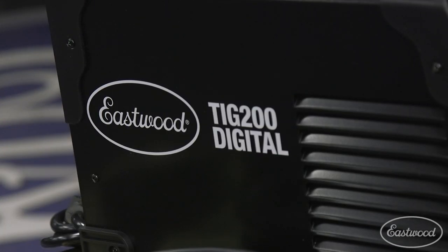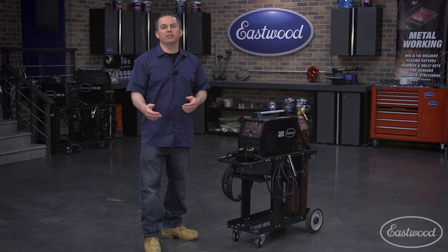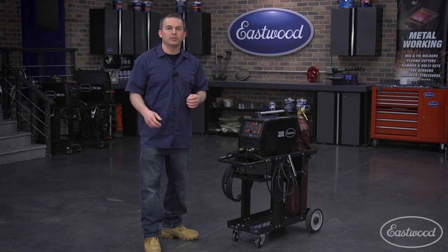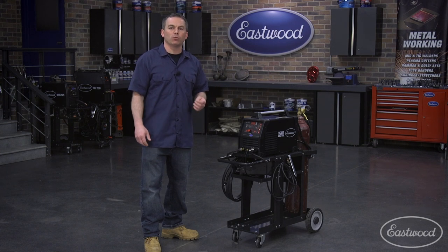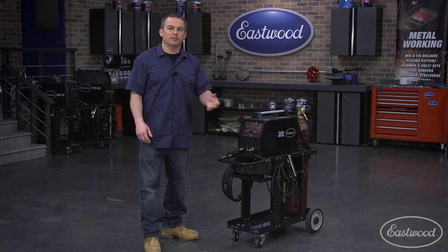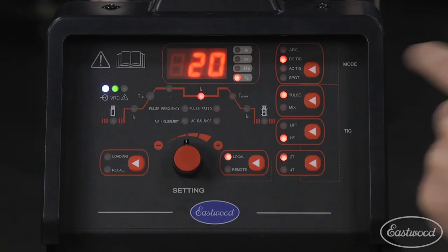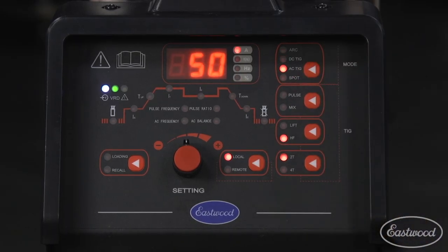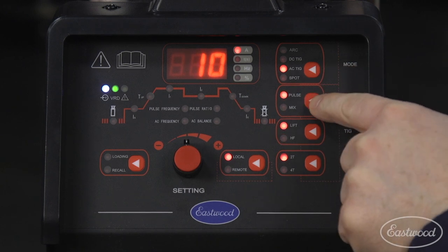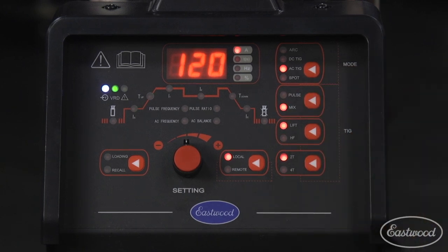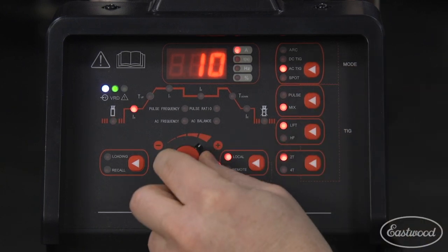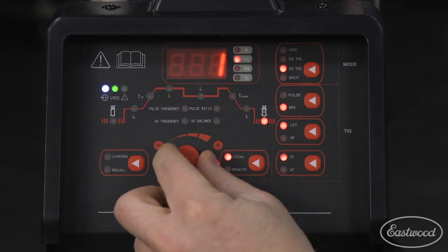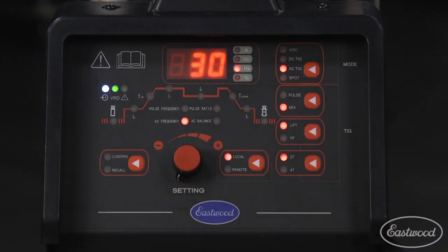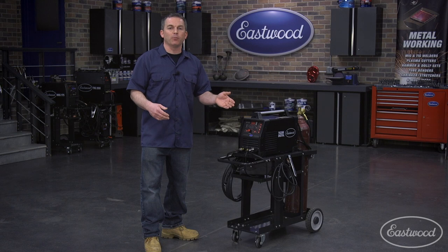The digital TIG also has mixed pulse. In many cases while welding aluminum with low amperages, the arc can be difficult to stabilize, so this machine adds a DC pulse while welding to do just that, stabilize your arc. To set your machine to mixed pulse, set your machine to AC, then mix. Then pick your parameters for AC pulse welding, as we talked about earlier. Instead of your current dropping to a lower AC amperage like it normally would, it will now drop to a set DC amperage for the arc stabilization you need.